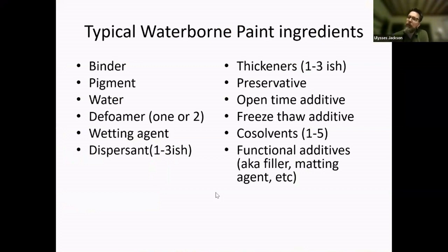In a typical waterborne paint, there's a lot of ingredients that we have in there for many different goals, right? And I like to think of each one as a personality. And so, you know, they all have to get together and function well. So here's just kind of a list of the typical things that would be in a water-based paint. It's usually right around 12 to 16 ingredients that each one has to play nice together. And since my company has a lifetime replacement guarantee, it means that we have to assure shelf stability, which we actually do with accelerated aging.